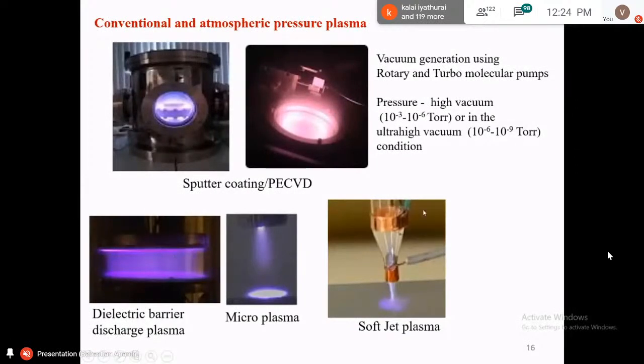In atmospheric pressure plasmas, there are many kinds: the dielectric barrier discharge, microplasmas, and soft jet plasmas. So what happens in dielectric barrier plasma? We have to apply a very high voltage to the electrode on top and the ground electrode. We should use a dielectric barrier because we cannot directly give power between the high voltage and the ground. It will create an arc, and that is not a plasma. So we have to utilize a dielectric. Then, due to this power, the gases inside these electrodes get ionized. This ionization gives the plasma. So we get a plasma like this.